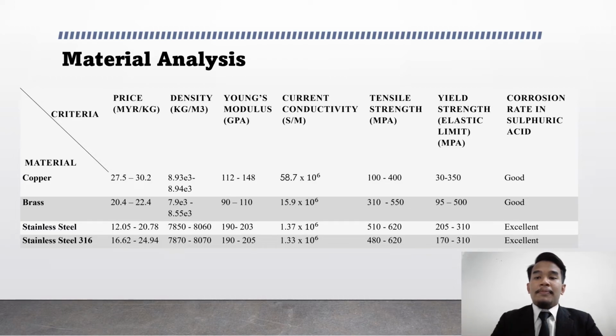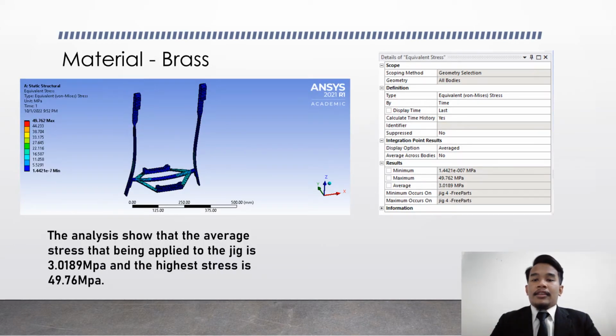Now, I will talk about the material analysis. The table shows the comparison for price, density, Young's modulus, current conductivity, tensile stress, yield strength, and corrosion rate in sulfuric acid for copper, brass, stainless steel, and 316 stainless steel. The figure shows the analysis for brass on design 4. The analysis shows the average stress that has been applied to the jig is 3.0189 megapascal, and the highest stress is 49.76 megapascal for this material, which is brass.